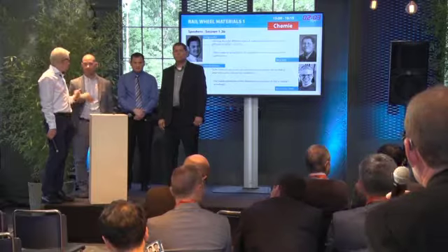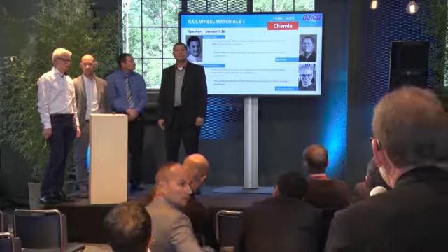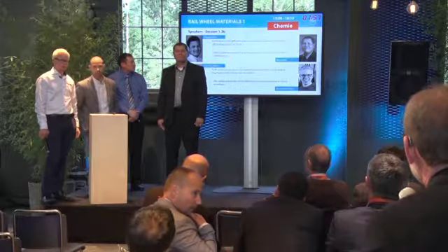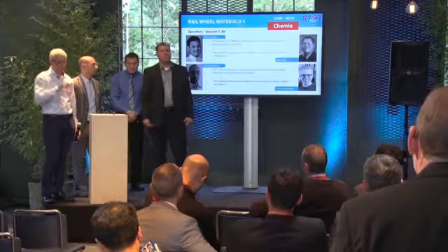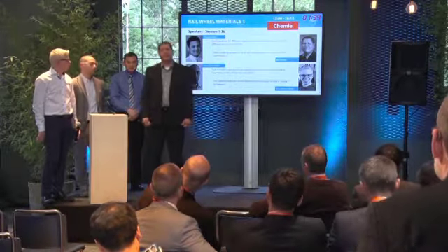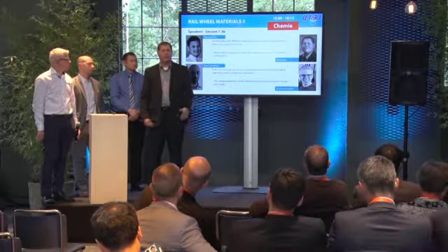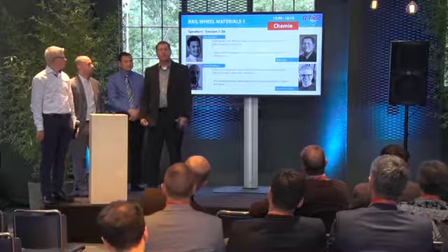Thank you. A question for Kerry. I have an interest in thermomechanical shelling, which you may share with me, but I was interested to know if there's any differences in the performance of those wheels with respect to thermomechanical shelling, or whether you've done any specific material tests, like high temperature tensile tests to characterize the material. We did some high temperature tests on all the materials, just at 540C. It was about the same kind of differences we saw in the room temperature tests at 25C. No great differences that we saw.